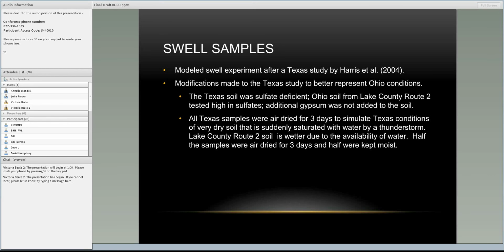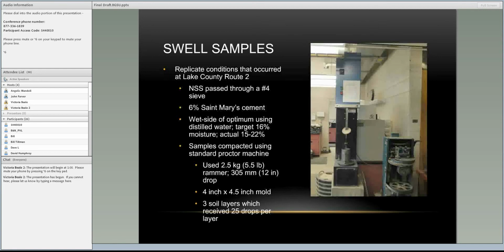To make the samples, we made them here at the ODOT facility. The soil, we used non-stabilized soil, and it was passed through a number 4 sieve first. We then added 6% St. Mary's cement to that, and we wanted it to be the wet side of optimum, so we were trying to hit a target of 16% moisture with the addition of distilled water, and the actual samples came out somewhere in the range of 15 to 22%. Some of them were 16, some of them were a little short, some of them over.